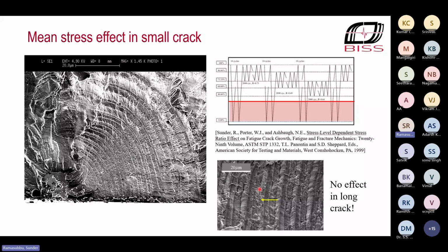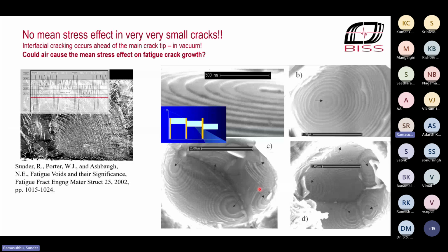And then one fine day, looking at the same fracture surface, but into one of the cavities left behind by a secondary particulate, I was shocked to find that the concentric rings, which show the progress of an interfacial crack that was separating the particulate from the matrix in the same aluminum alloy, was showing a constant growth rate in all three steps. Now, this is an extremely small crack. This is probably the smallest crack any of us has seen. It's about 120 nanometers in diameter. And it's growing at a constant rate, independent of the applied stress ratio. This is in the same material, same specimen, in fact, but it's a small crack which is not seeing the effect. And I came to what at that time seemed a preposterous conclusion, that perhaps it's the environment.